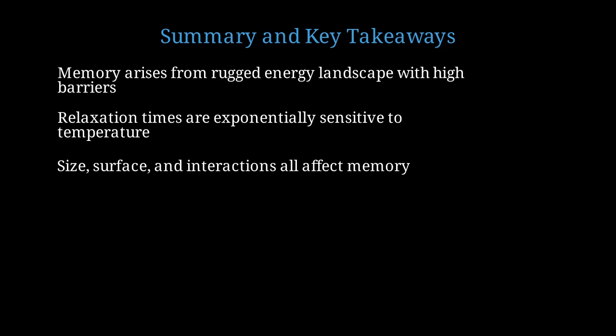The exponential temperature dependence of relaxation times means that modest temperature changes can shift timescales from seconds to years, or vice versa. Memory behavior depends critically on particle size, surface effects, and interparticle interactions. All three must be considered for accurate predictions.